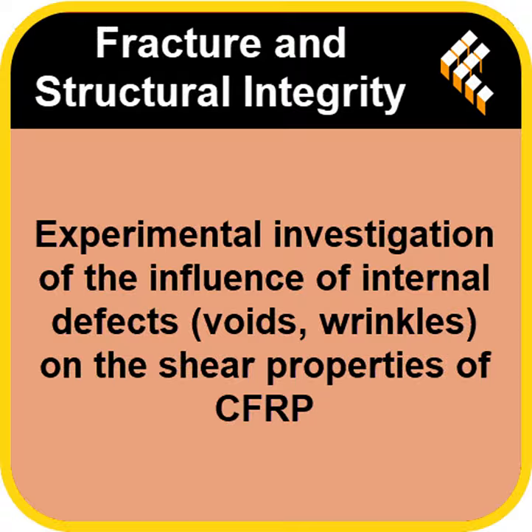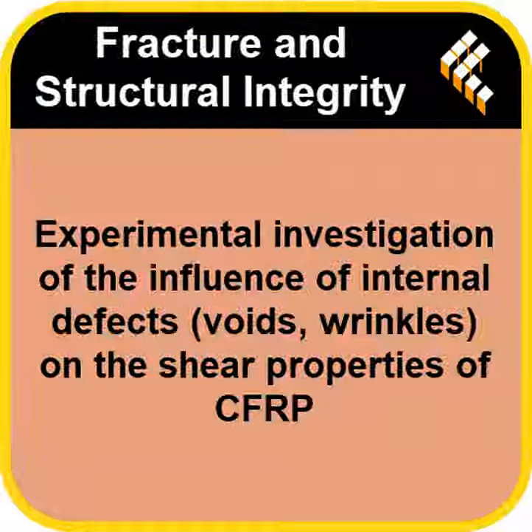But here's the tricky part, the paradox really. These things are built in layers, right? Exactly. Layer upon layer of carbon fiber infused with a polymer resin. And that layering process, it's not always perfect. You can get these hidden flaws baked right in. Things like voids or wrinkles in the fibers. That's the core issue. These aren't just surface scratches, they're internal defects. Yeah. And they can be really tough to spot using standard inspection methods.